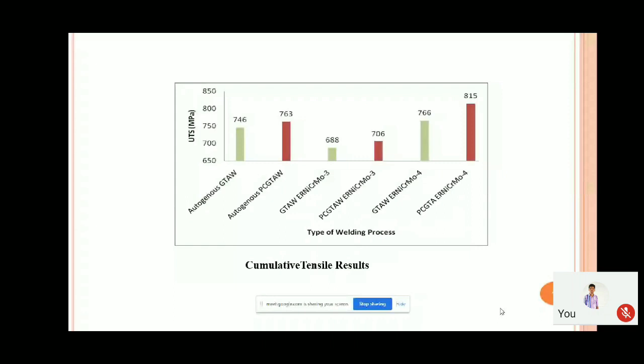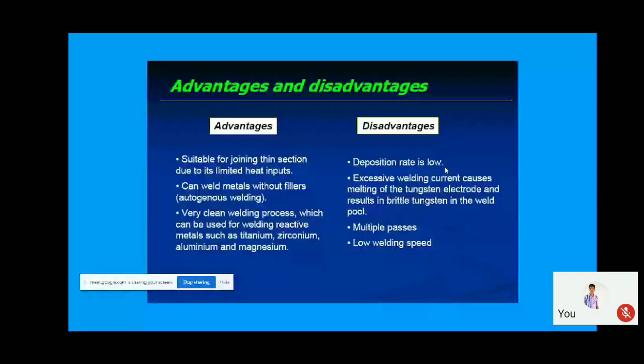So what are the advantages and disadvantages, sir? So it is suitable for joining the thin section. GTA welding is suitable for joining the thin section due to the limited heat input. The deposition rate is low, as I told previously. Deposition rate will be low as compared to MIG welding. So it can weld metal without the filler material. Autogenous welding is possible. Can go up to the welding of 3 mm thickness, not more than that in the autogenous case.